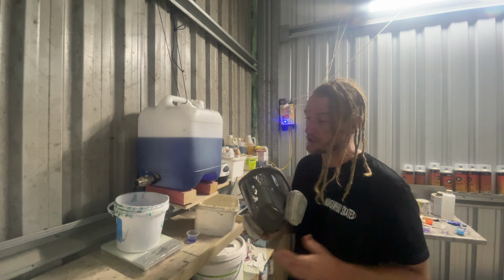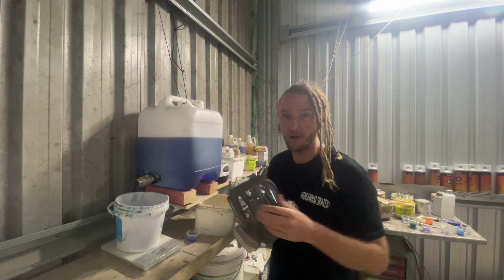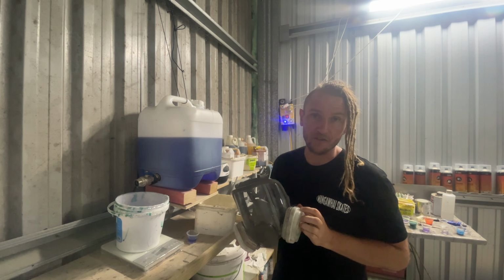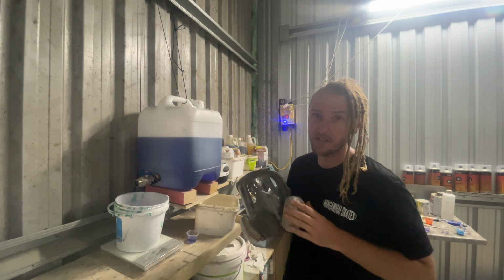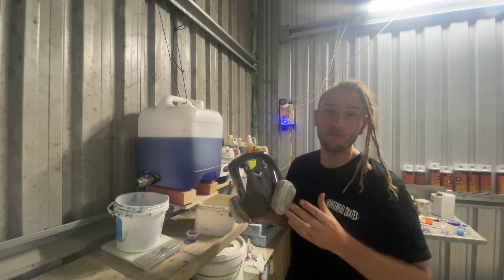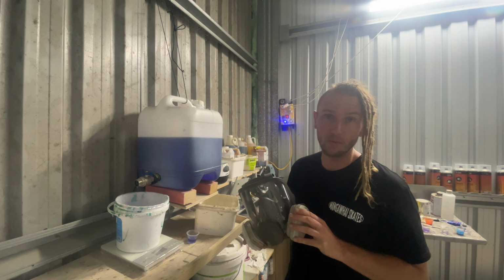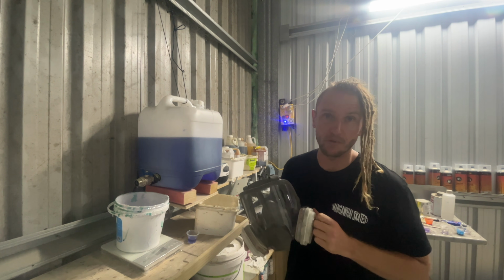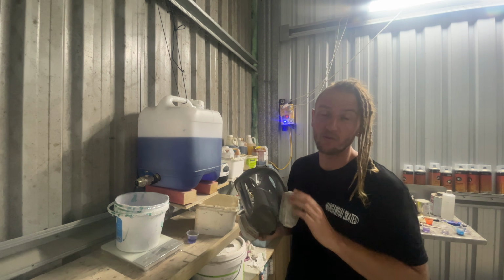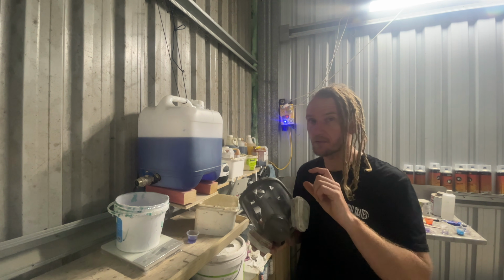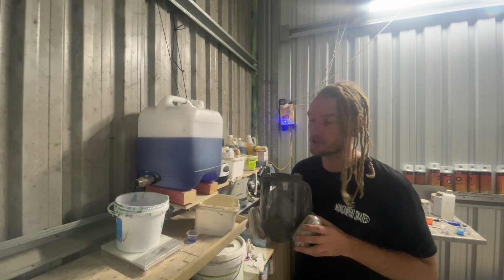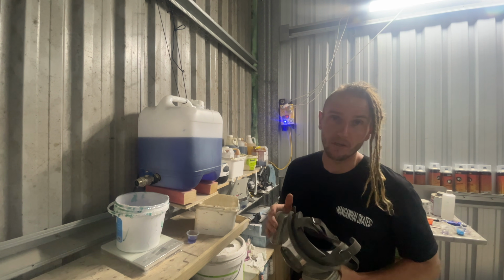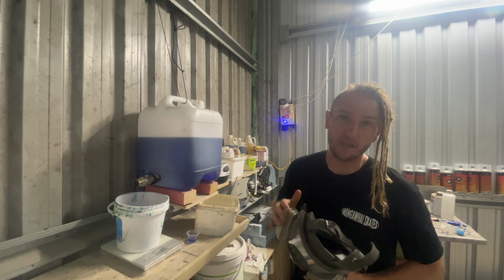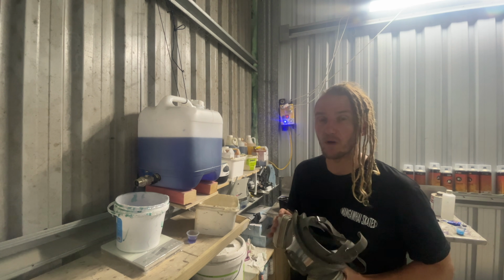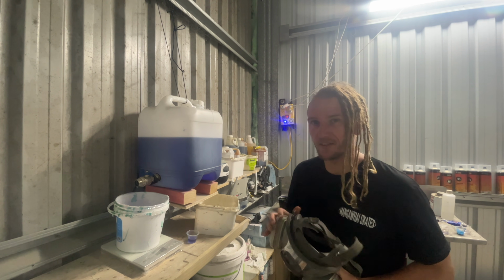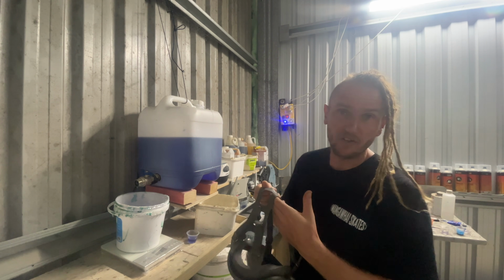done. So we're going to pour 700 mils of poly resin. That means that 1% of 700 mils is going to be 7, and 2% of 700 mils is going to be 14. So we're going to do 14 mils of wax additive in our 700 mils of resin, and we're going to go slightly lower than 1% of catalyst, so slightly below 7 mils, just because of the temperature. So considering 1% is 7 mil, I will probably mix up 5 mil of catalyst, so we'll go 2 mil less than 1%. I wouldn't want to go too much under that. So we'll stick the mask on and we will mix up our resin.